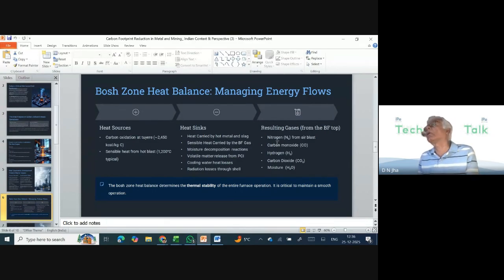Apart from that, if the CO that you produced in the Bosch zone has not been able to reduce the oxide, then it remains as CO in the top gas. Is that clear? So we have carbon monoxide, we have carbon dioxide, we have H2, and the H2 after reduction generates H2O. Also, the burden moisture generates H2O. So essentially, the gases are nitrogen, CO, H2, CO2, and H2O. These are the gases which are there at the top of this.